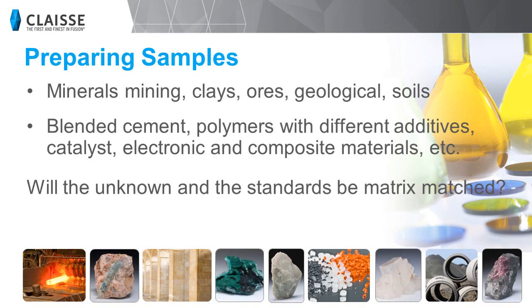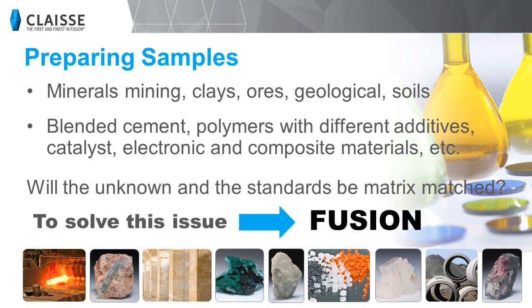Having said that, we have to keep in mind that the standards used when preparing an XRF calibration curve should be similar to the unknown samples that need to be analyzed. When preparing natural samples such as minerals, clay, or geological and soil samples, it is practically impossible to know if the standards and unknown will be matrix matched. It is also the case with industrial products that can be mixed together with natural samples such as blended cement, polymers with different additives, catalyst, electronic, and composite materials. Fusion is the solution to this issue, and we will prove it in the next slides.